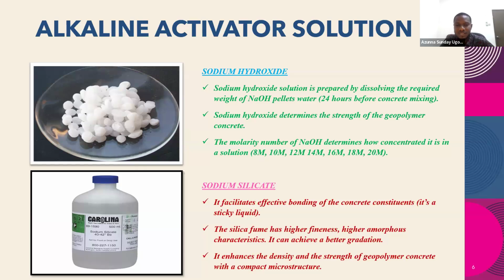Like I said earlier, it's a combination of sodium hydroxide and sodium silicate. The sodium hydroxide solution is prepared by dissolving pellets. This, what you see there, the white pellets, is sodium hydroxide. That is how you buy it. That is how it's supplied from the company. So you prepare the solution by dissolving these pellets in water. What determines the quantity you use depends on the molarity of sodium hydroxide you want to use in producing your concrete.